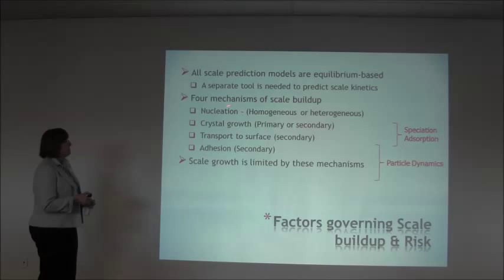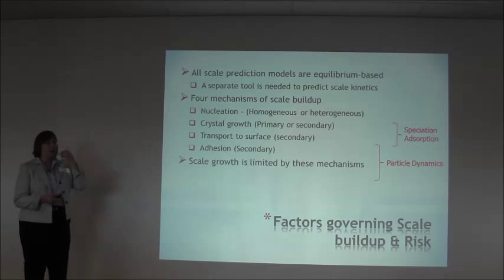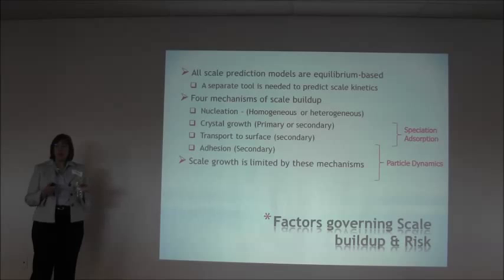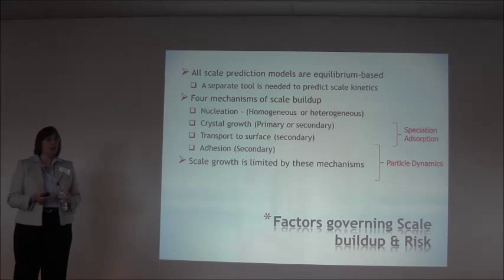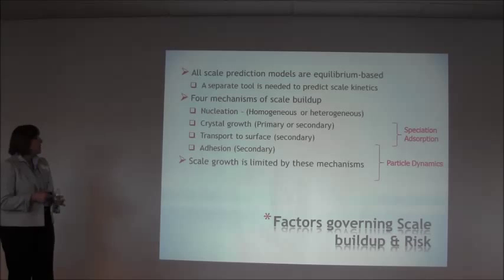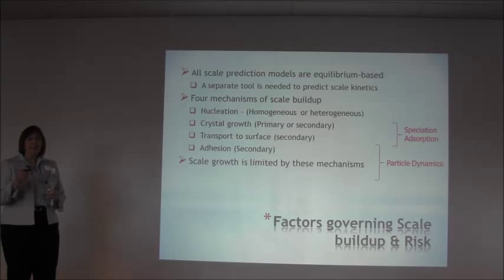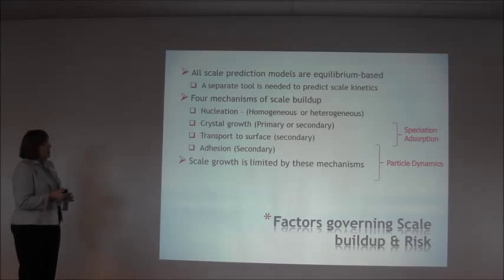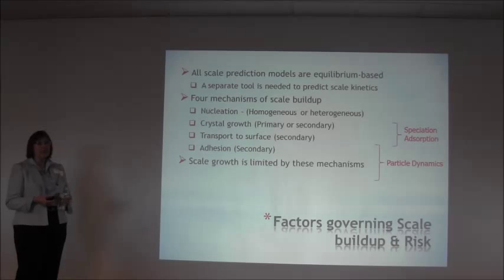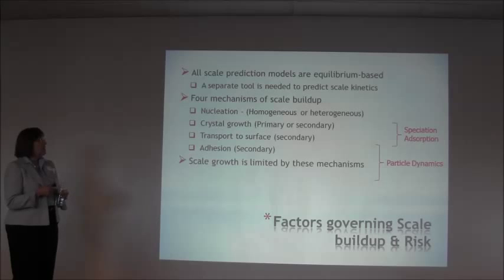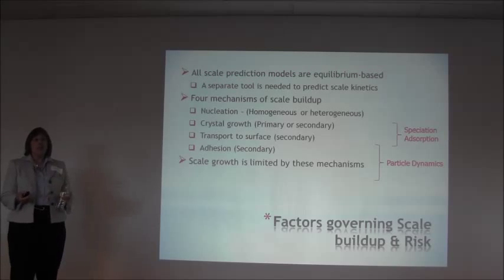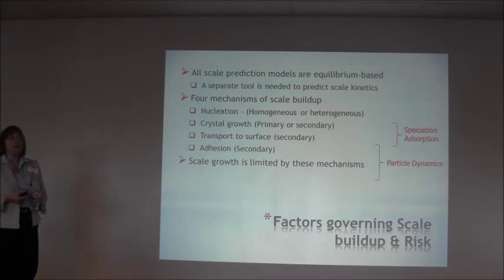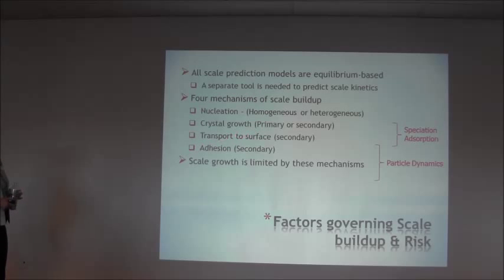I'm so glad Steve talked about this because I'm not going to talk about it. And actually Vince did too, the difference between a scale and a deposit. We don't actually go there. We're only talking about energy. We're only talking about the thermodynamic driving force for scales to precipitate. Nucleation is an issue. Does it have something to latch onto? Is it going to latch onto the wall? I was thinking of Vince's description where you put the one drop into the one piece of the scale to let the nucleation start, and whammo, everything starts. So there's all kinds of mechanisms for scale buildup when you get to finally understanding what's going to happen. Is scale going to be a problem? All we really want to talk about as thermodynamicists is basically, is the driving force such that you have a problem? Is your system going to have a problem? And then, sure, all these things are going to be hit to try to decide whether or not you have a problem in terms of crystal growth and things like that. Okay.